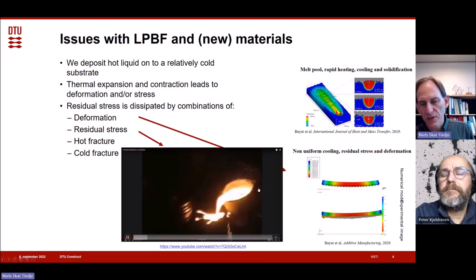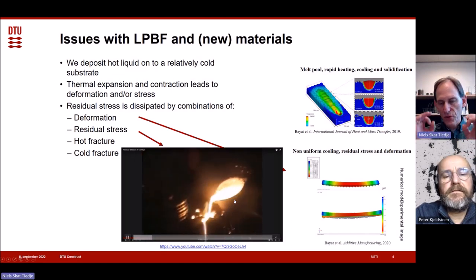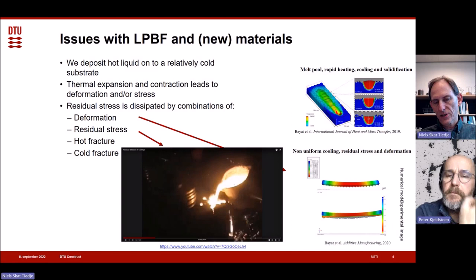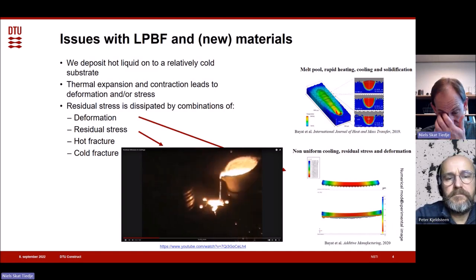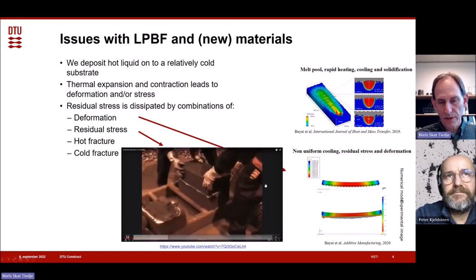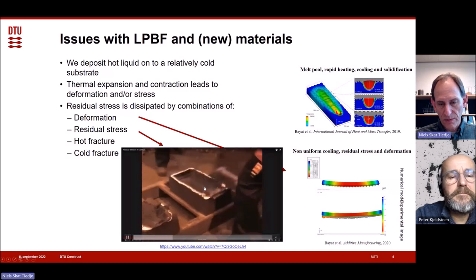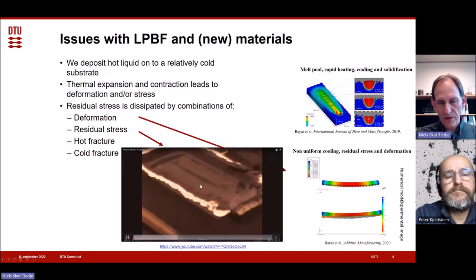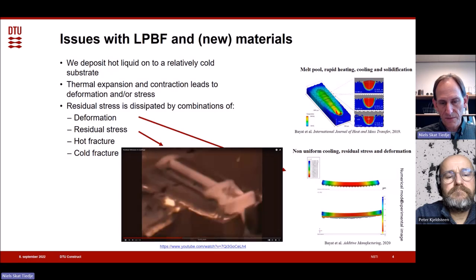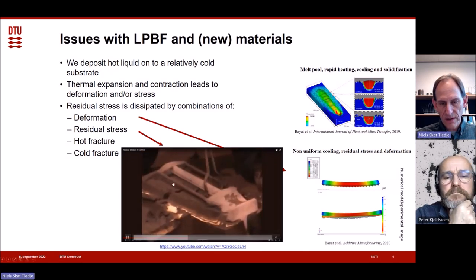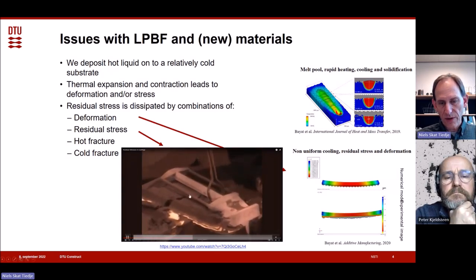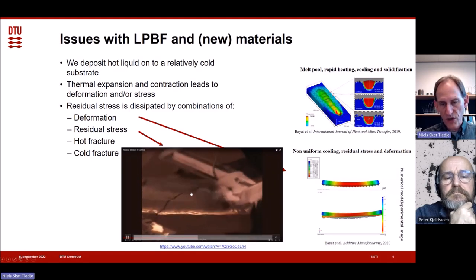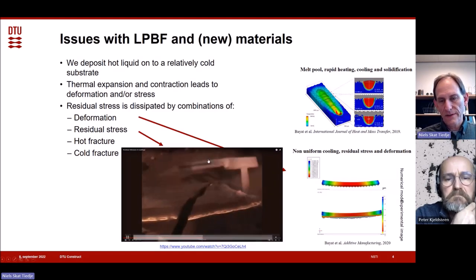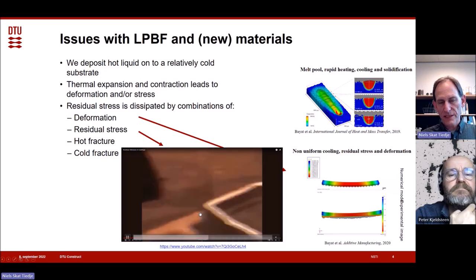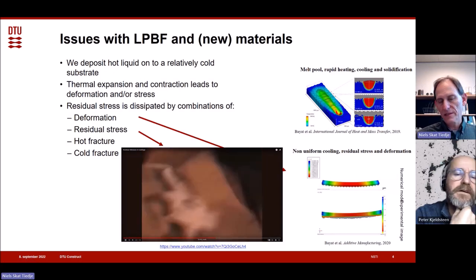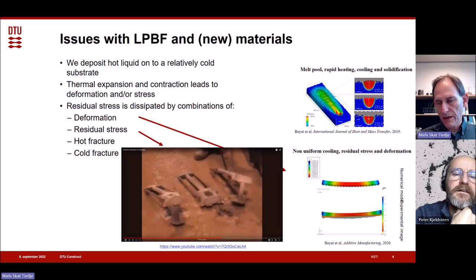So they cast what is called a stress lattice. You have two thin bars connected to a heavy, thick bar at the center. We'll get to see a proper picture of it in a moment. Here's the casting they open. It's a bit difficult to see, but we'll get a proper picture later. Here you see the heavy section and two thin bars. And of course, the thin bars will solidify quickly, contract, and build up strength. And then the center bit solidifies, and then it contracts, and that means that the two thin bars are under pressure.